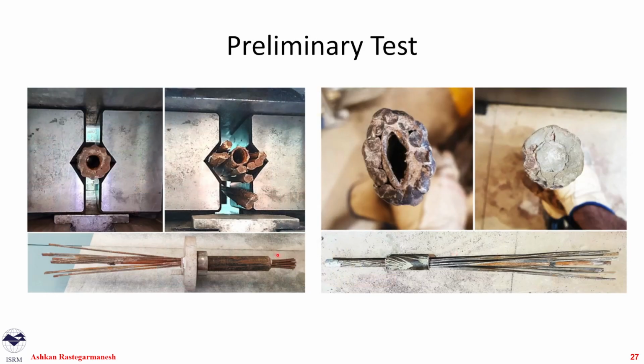We realized that, okay, a few issues. The grip of the machine will break the cable, and when the cable breaks, it disintegrates. So we realized we have to put some welds around our cable to make sure that if one of the welds fails, the cable doesn't just end up like this. We realized that we need to fill out our cables. Most of them are already filled, but our hollow cables, which were our 9S, 10S, and 12S, we need to fill them out because when they are empty, this grout hole, or this breather or bleeder tube inside the cable, is going to get crushed.